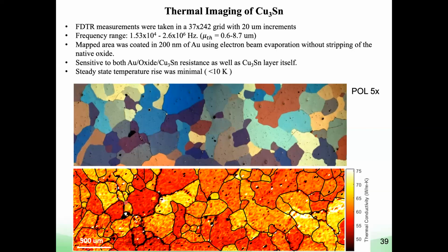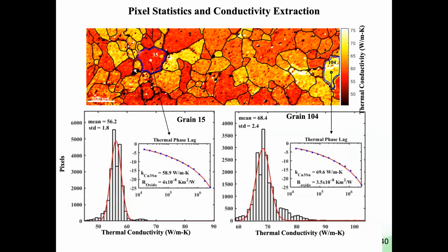So we did this thermal conductivity map, and these black lines in between are just to guide the eye at the grain boundaries. For each one of these grains, my student made an outline of the perimeter of it and used that to do some analysis of the thermal conductivity over that grain. So we were able to get the average thermal conductivity and standard deviation for each grain in this image. So here are two representative ones.